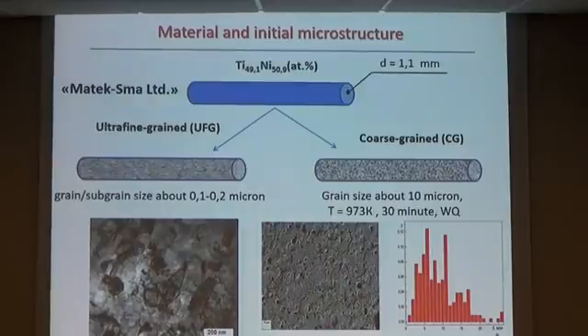Two types of specimens produced by Matek company, with ultrafine grain structure with grain and subgrain size about 0.1 micron. It is the microstructure. And specimens with coarse grain structure, with grain size about 10 microns, after recrystallization annealing.